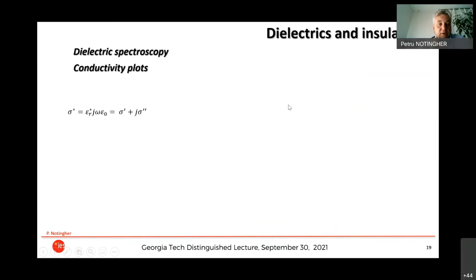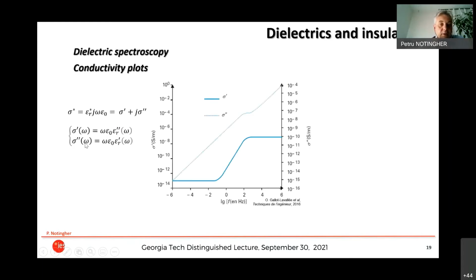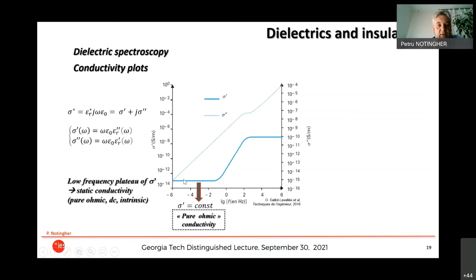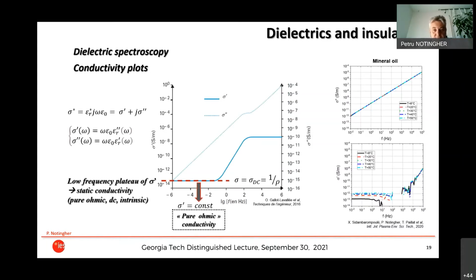Well, of course, it is very easy to draw a conductivity plot because the relationship between conductivity and permittivity is just the permittivity multiplied by omega and epsilon 0. So you can draw a real part of the conductivity and an imaginary part. And if you plot the real part, you see very well when you reach a plateau, the conductivity is constant. So this is the value of the conductivity that you want to measure. So this is an example done on mineral oil. So you see very well the conductivity of the oil with respect to several temperatures. So of course it increases with the temperature, which is perfectly normal.